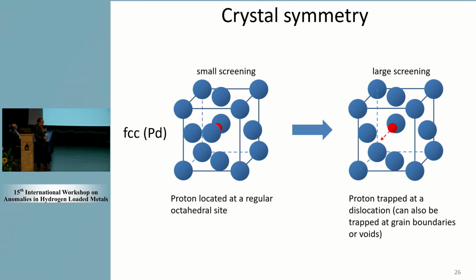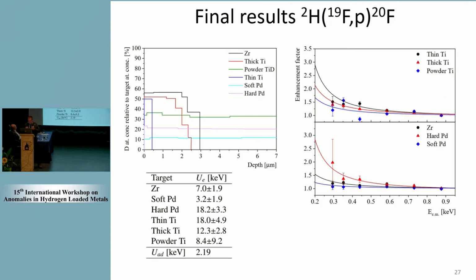In this case, it was cold rolling of palladium that probably produced, I mean, definitely there was some stress in this target. You saw that it's all deformed. That could produce, for example, such vacancies, and also some other defects which are probably responsible for large electron screening. So these are our final results, what we have so far.